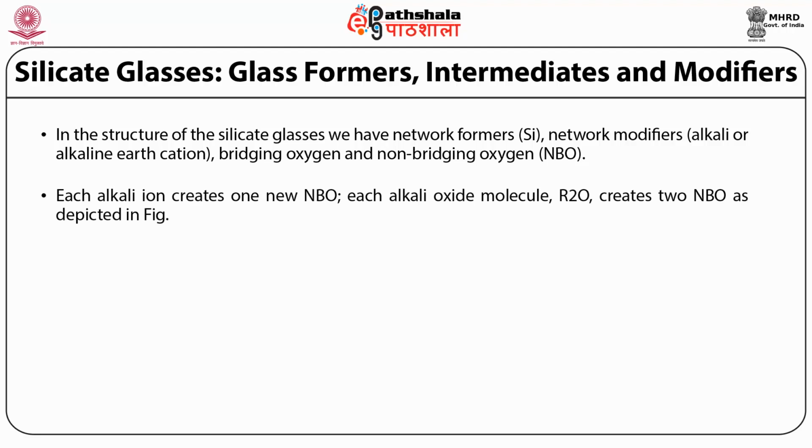Each alkali ion creates one new NBO, that is non-bridging oxygen, and each alkali oxide molecule R2O creates 2 NBOs, as depicted in this figure.